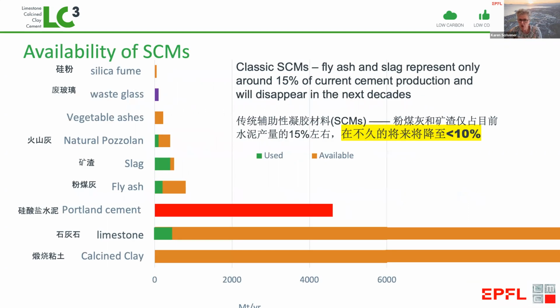Now, this is not new. We've been using substitute materials, particularly slag and fly ash, for many, many years. The problem is that the amounts of slag and fly ash available today are really quite limited, and these will decrease drastically in the future.